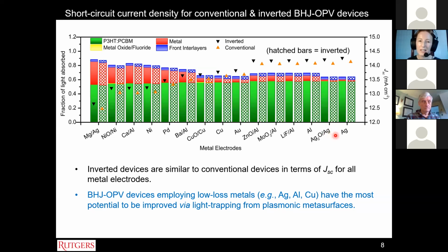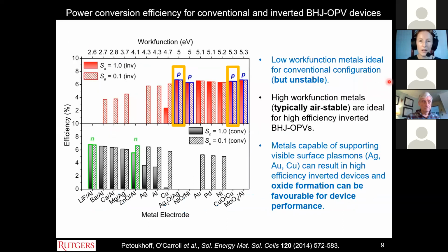And so from this study, we thought that using silver oxide on silver might be a good way to help us stabilize a silver electrode and improve its work function so that we could get a good open circuit voltage as well as good short circuit current density. And here again, this is where we did the calculation of the power conversion efficiency, again showing that low work function metals are ideal for the conventional configuration, but they're unstable. So they create high efficiencies in conventional devices. And then high work function metals, which are typically air stable, are ideal for high efficiency inverted BHJ photovoltaic devices.